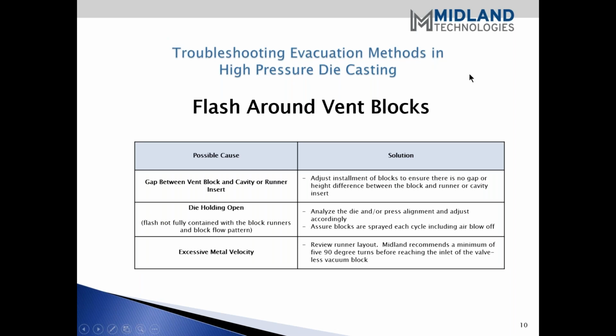Well, the next issue that we see is flash around the vent blocks. The first possible cause we have here is the gap between the vent block and the cavity or runner insert, and this again gets to the adjustment and installment of the blocks. Larry, if you want to go through that in a little more detail. Yeah.